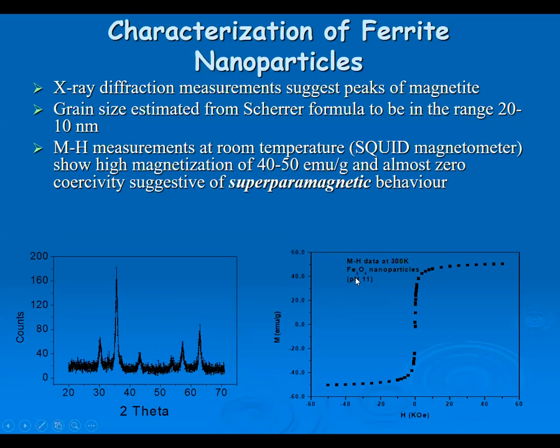I will show a typical one, Fe3O4, which showed superparamagnetic behavior. You typically know that this is a hysteresis curve in magnetic materials. You have a wide loop, but when they become superparamagnetic, the loop width, the coercivity, is near zero. As you can see from the X-ray data, students will soon be doing some analysis on this, I hope. The widening is a measure by which you can estimate the grain size, and we typically got it in the range of 10 nanometers and 40 to 50 emu per gram of magnetization. This is a signature of superparamagnetic behavior, which would render it useful for biological applications.